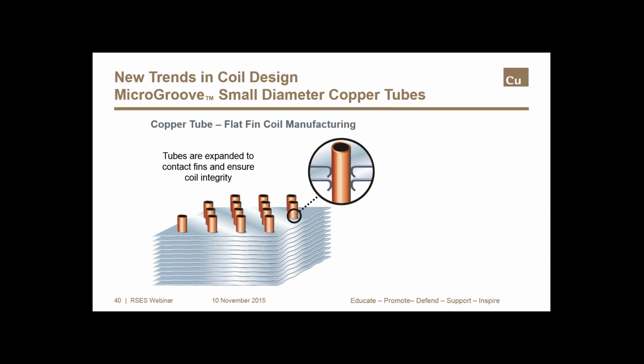The bullet is a bit larger in diameter than the tube, and the expansion of about 10% or so does the job. With a trend towards smaller diameter tubes, this process has certainly been doable, but it's become a more delicate and slightly longer process than it is for larger diameter tubes. Very recently, a major equipment manufacturer that builds coil manufacturing systems for most of the world's coil suppliers has introduced a new pressure expansion process.